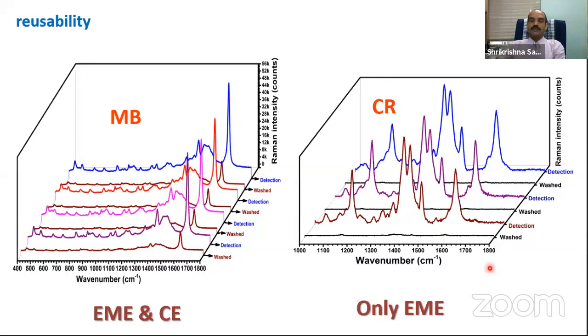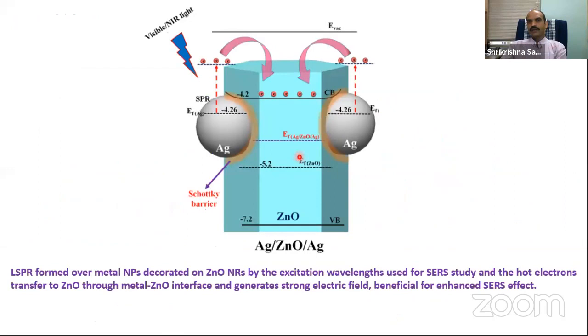Again, I wash it, again I detect it and wash it. It means there is no chemical enhancement, only electromagnetic enhancement, which means this dye is only physisorbed on the surface. On the other hand, if it is methylene blue, you can see that if I just wash it, I still get some intensity. Again, I do the detection, again I wash it, the same water washing, and I'm not getting zero intensity. It means that for methylene blue, where you have electromagnetic enhancement as well as chemical enhancement, I will not be able to reuse it by just washing with water, but I have to do something else.